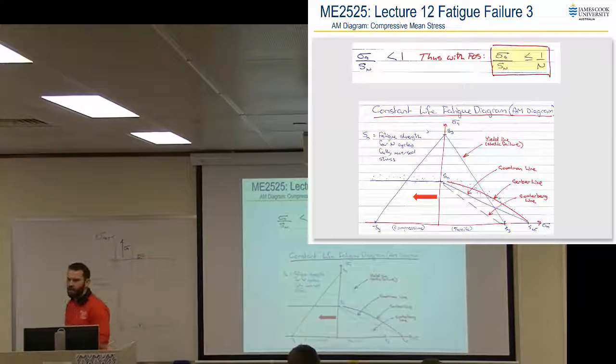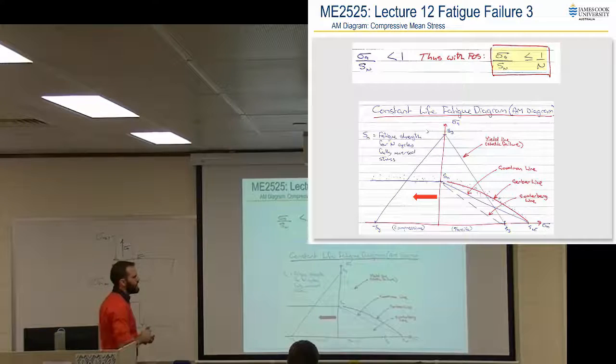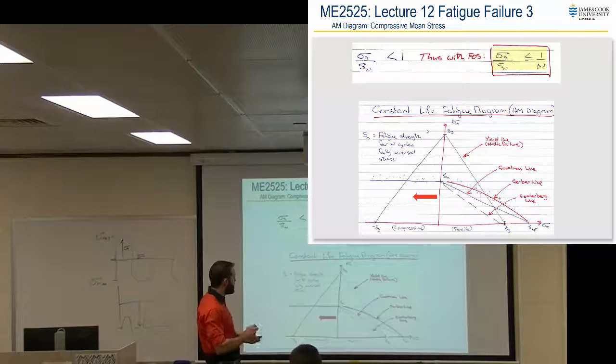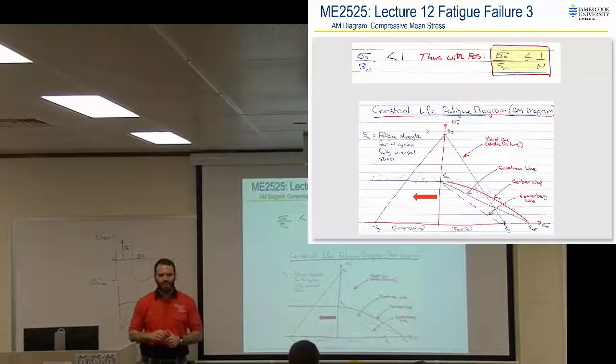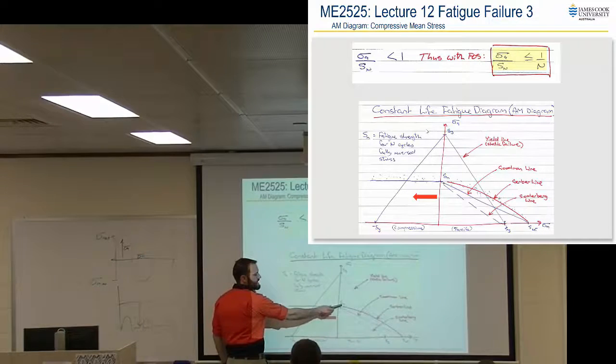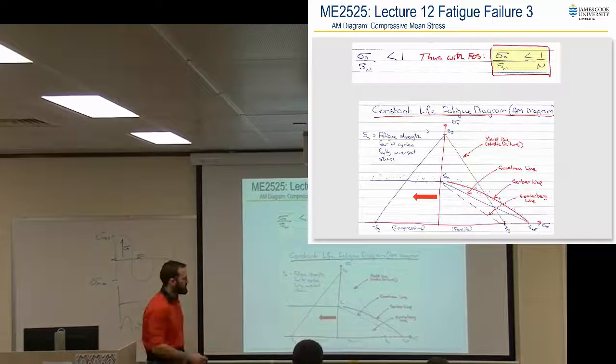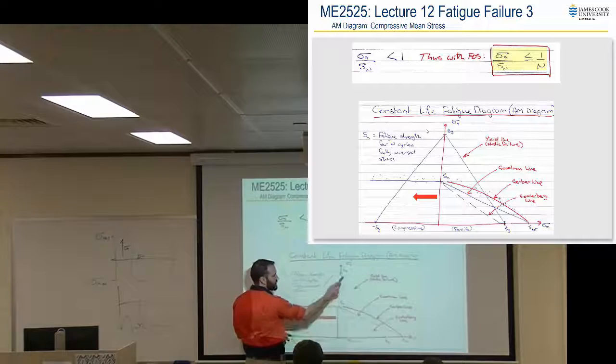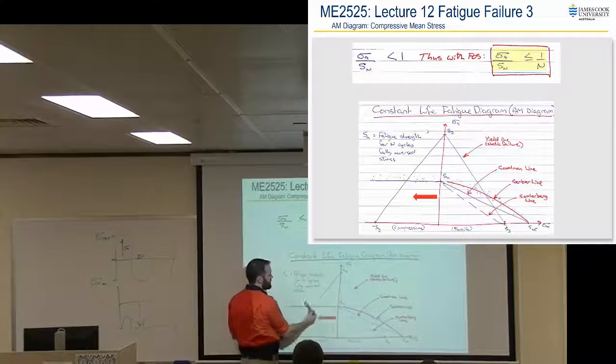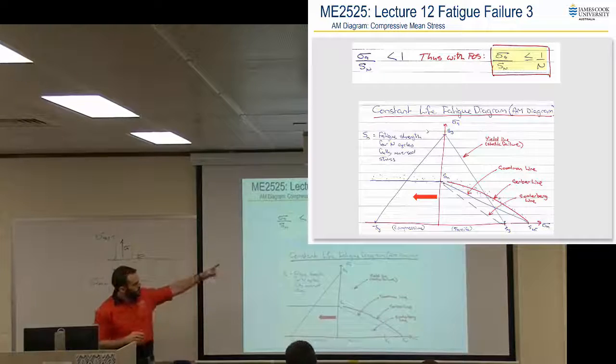And what they've found is that largely the increase in mean stress doesn't have a detrimental effect on the actual strength. So you can have a very large compressive mean stress, and really you're only limited by the fluctuations still. So everything I said before is completely invalidated in compression. Alright? In compression, all you do is make sure you're under SN, the exact same way that we've analysed with the fully reversed case up till now. It's just that instead of analysing the whole stress, you just calculate what sigma A is and you compare that to your SN. So that's the equation up there.